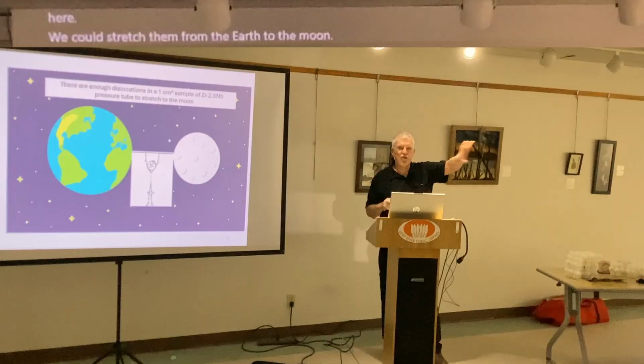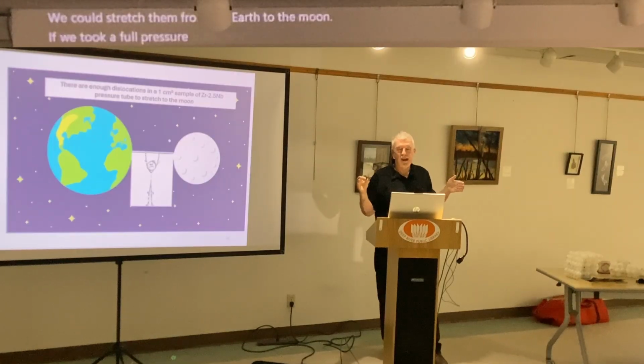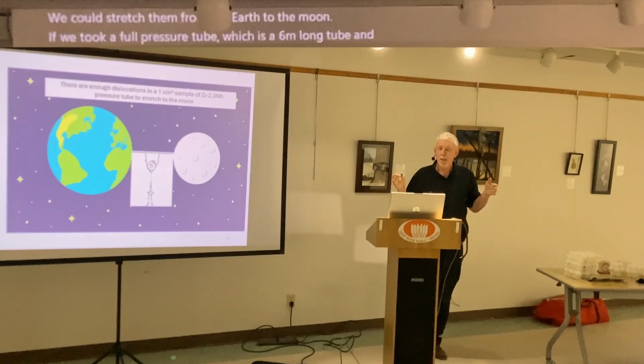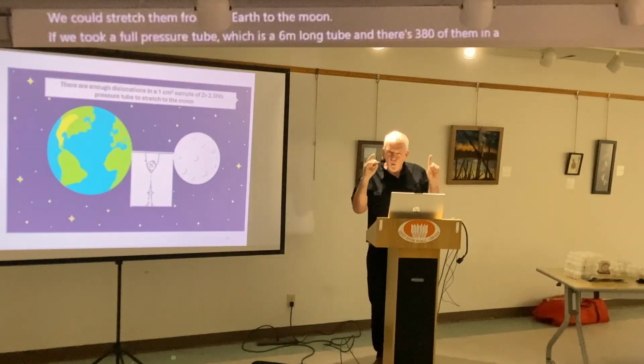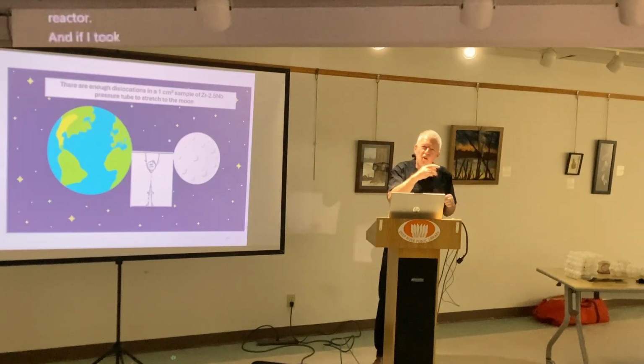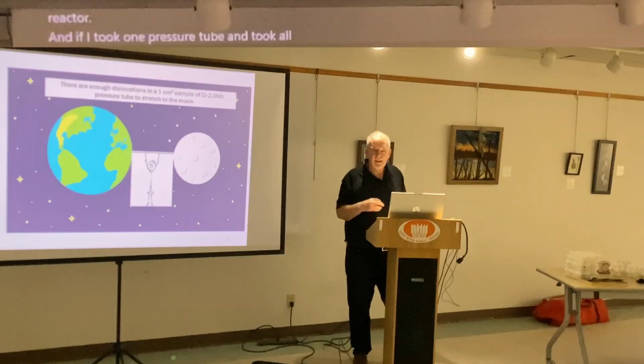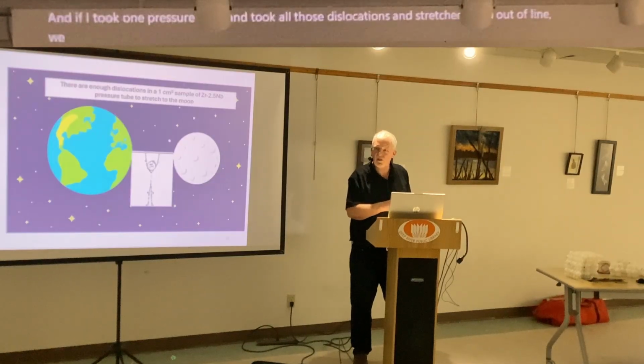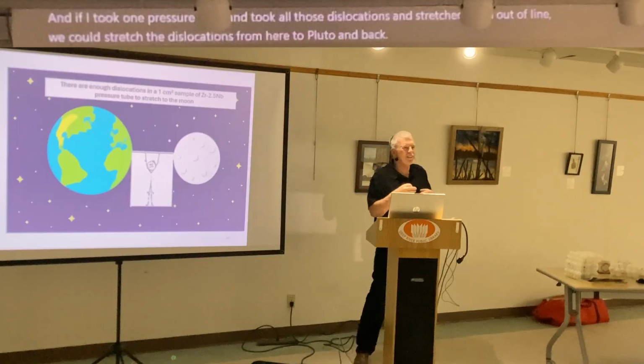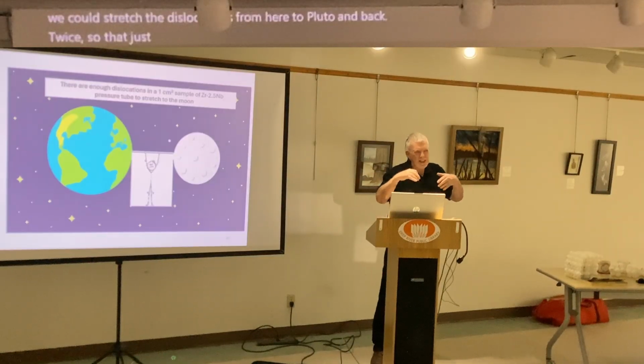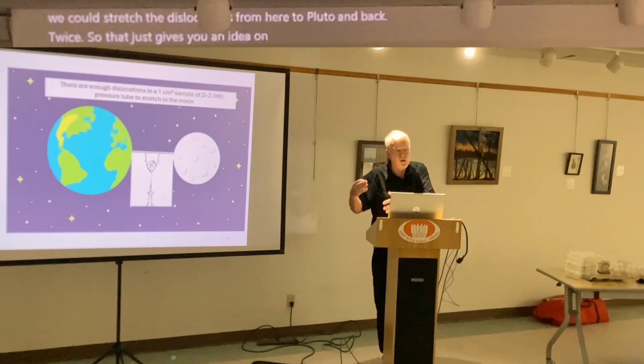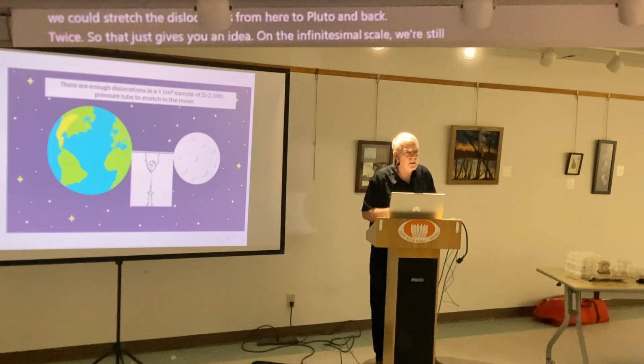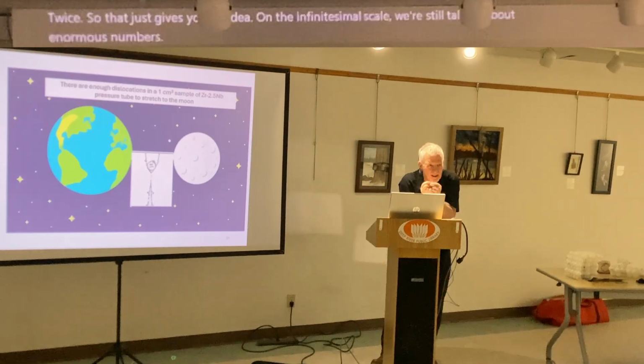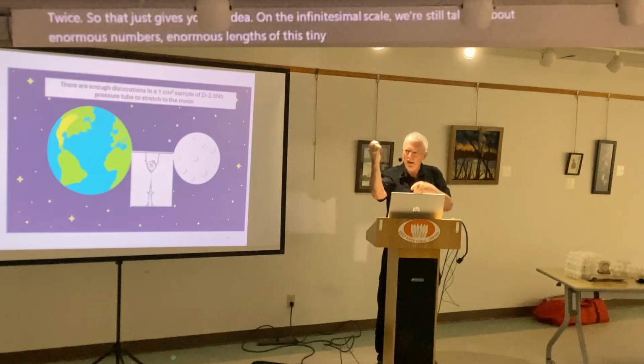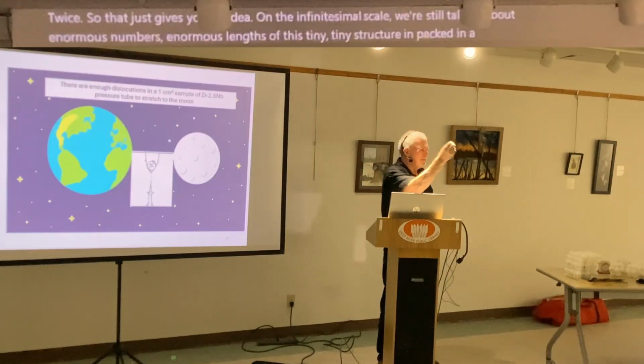If we took a full pressure tube, which is a 6 meter long tube, and there are 380 of them in a Calandria reactor, and took all those dislocations from one pressure tube and stretched them out in a line, we could stretch the dislocations from here to Pluto and back twice. So that just gives you an idea of the infinitesimal scale. We're still talking about enormous numbers, enormous lengths of this tiny, tiny structure packed in a little tiny piece of metal.